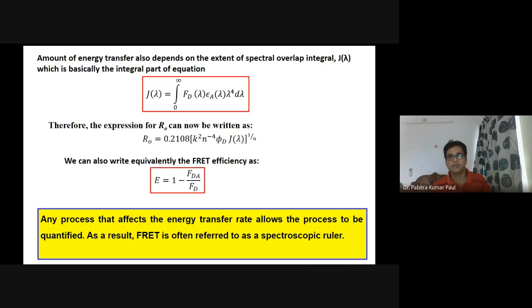Here FDA, the numerator, is basically the steady state fluorescence intensity of the donor in presence of the acceptor, and the denominator FD is the steady state fluorescence intensity in absence of the acceptor. So by considering this ratio and multiplying by 100, we can express the efficiency as a percentage. And so it cannot exceed 100%.